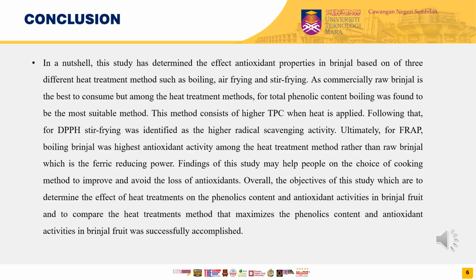As I can conclude from this study, the objective of the study to determine the effect on antioxidant properties in brinjal based on 3 different heat treatment methods such as boiling, air frying, and stir frying was successfully determined. Commercially, raw brinjal is the best to consume, but the heat treatment methods also can contribute to the antioxidant benefit for the consumer. Firstly, the total phenolic content is highest for the boiling method, for DPPH the stir fry method, and lastly for FRAP antioxidant activity the method is also boiling, similar to the total phenolic content.